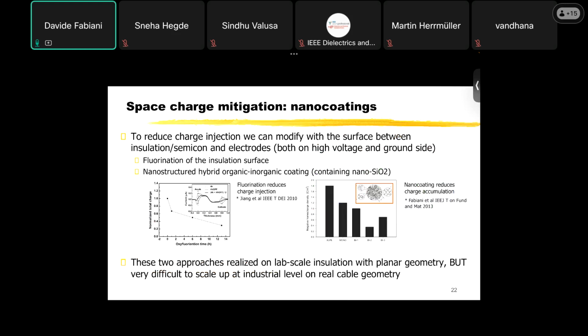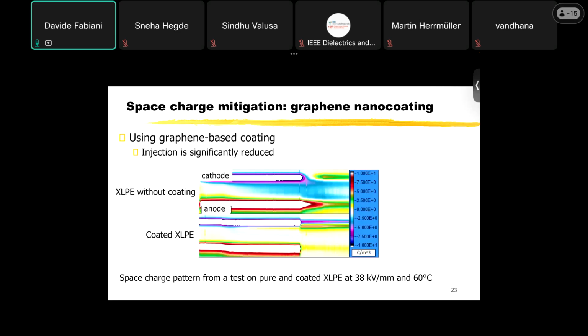There are many ways, introducing, for instance, deep traps on the coating, so not in the bulk, but on the coating, by creating a fluorination of the insulation surface, or a nanostructured coating by, for instance, using inorganic coating containing nano silica, okay? And as you can see here, there is quite a huge reduction of space charge with both fluorination and this nanostructured coating. What we did also is to apply a graphene-based coating by using a spray, a graphene spray, okay?